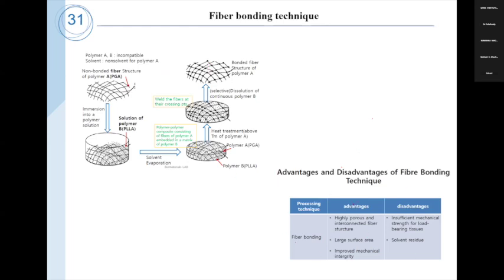The advantages are a highly porous and interconnected fiber structure and a large surface area, because this type of technique produces fiber structures. We can also improve the mechanical property because one polymer is bonding onto the fiber structure. However, it has some disadvantages, like insufficient mechanical strength for load bearing tissues, especially bone tissues. Also, solvent residue is sometimes a problem, as it can retard cell growth and differentiation.